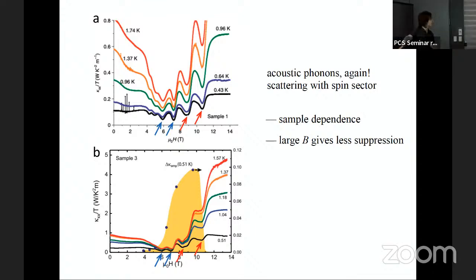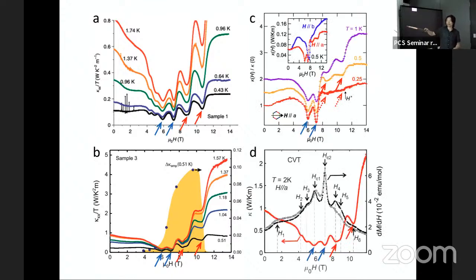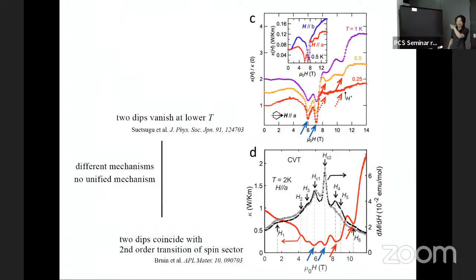So, this suggests that the phonons may be interacting with the spins, giving these suppressions, and maybe the dips are because the suppressions are somewhat stronger. And if we look at the further data by other experimental groups, then we note two features. First, as you just suggested, it turns out that these two dips coincide with the places with high magnetic susceptibility. And this higher magnetic susceptibility is because the spin sector has some second order phase transition that is well understood. Some spin order changes slightly. And it turns out these two dips coincide with that. So this strongly suggests that these two effects are related.